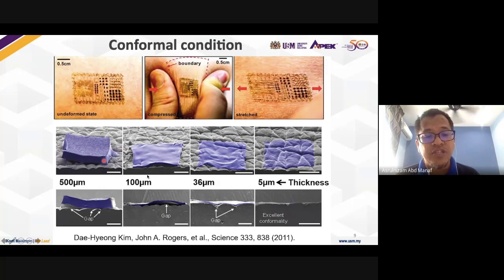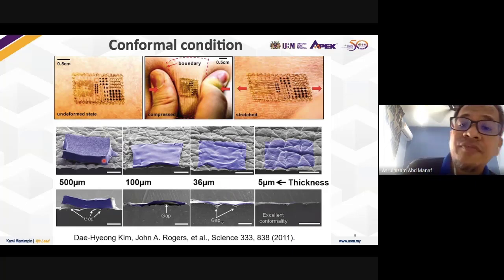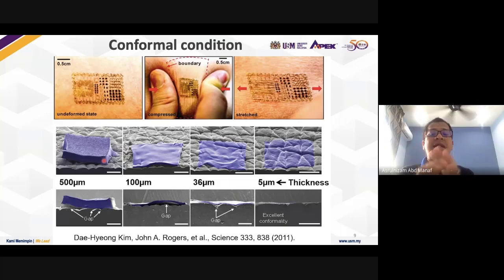So this group went to 100 micrometers, and you can see an improvement, but there is still a gap. They cannot follow the conformal structure of the body skin. Then they went to 36 micrometers, with some improvement, but after they reduced it to 5 micrometers thickness, you can see very good conformity with the skin structures. The latest thickness is from the group at University of Tokyo. They presented a 1 micrometer thickness substrate, and on top of that they have an array of OTFT transistors. This is from 2011.